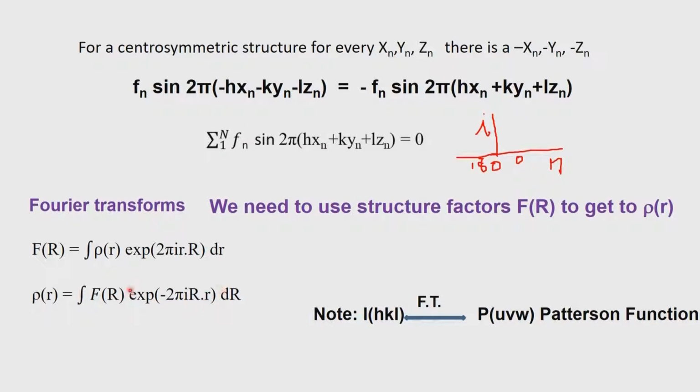We actually estimate these phases by various means, because phase by itself cannot be experimentally determined, nor can it be accurately estimated to the accuracy that we require in a structure determination. So, therefore, this is always an approximation which will result in a nearby phase being estimated. In that context, the previous discussion we had on the possibility of a centrosymmetric molecule having a phase of 0 or 180 gains a lot of importance, because we have only two possibilities for every reflection, and as a consequence the structure solution protocols become easier. We will evaluate them a little more closely later on.